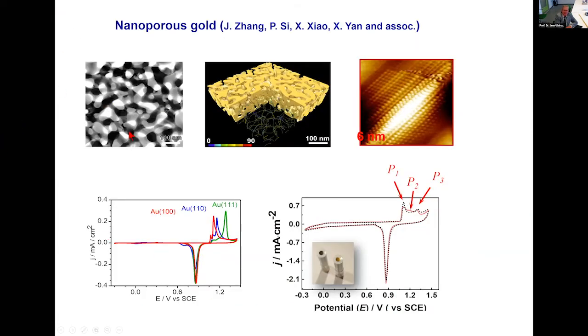Nanoporous gold, this is what it looks like. And this is another way it looks like. And this is a model of nanoporous gold. Well, you can see nanoporous means, some people would say non-crystalline. But you can see it's not so non-crystalline that it really matters. It's in fact locally quite crystalline. This is atomic resolution. And the voltammograms for the nanoporous gold electrodes are quite well resolved, and the different gold facets 111, 110, and 100 can surely be identified.